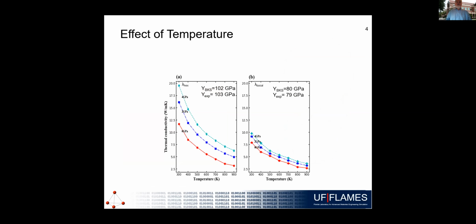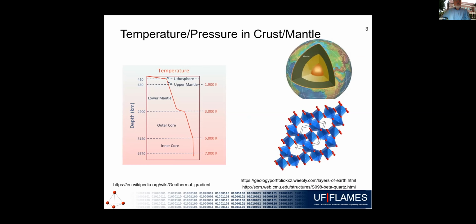And so this is some simulation results. Silica has a hexagonal structure. What we're seeing here is, in the hexagonal direction and the basal direction, the temperature and pressure dependence of the thermal conductivity. The range here is 20 down to 2. This is kind of the middle range, as we saw in Professor Snyder's presentation. Low thermal conductivity materials are sort of 1 and below. High thermal conductivities are maybe, depending on your application, 100 or more. So these are modest thermal conductivities.